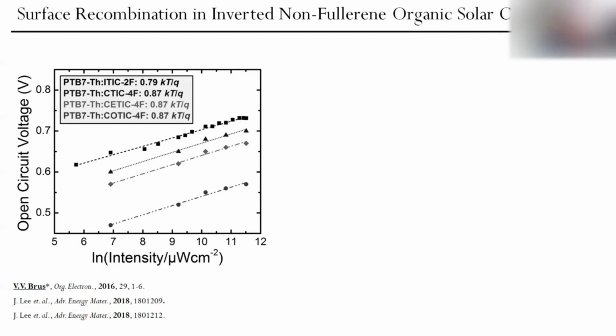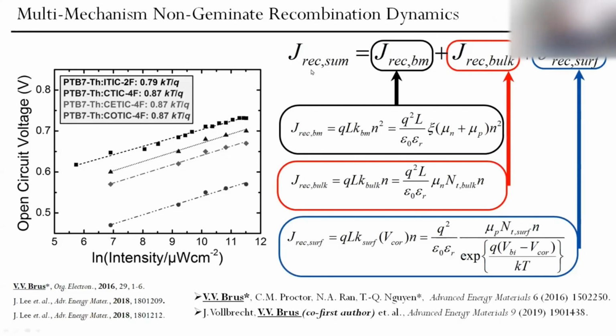And trap-assisted recombination in these devices, organic solar cells and also perovskite solar cells, which share the same device structure configuration, should also be distinguished: there is trap-assisted recombination in the bulk of the active layer and trap-assisted recombination at the interface between the active layer and the electrode. They have different influences on the performance of solar cells. Both of them have a negative influence, but they are different in terms of changes in parameters. So here we have an equation which describes the total recombination current.